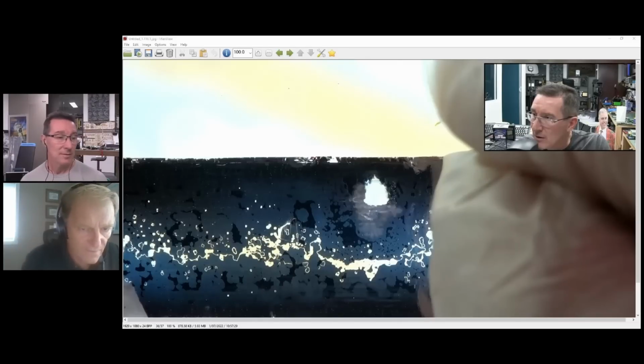So when you get those little micro arcing points, you actually vaporize that electrode material, and as it cools, it precipitates around that failure site. So if we could blow this up a little bit more with a SEM or something like that, we would see a little dark halo around that white point of failure. I might put this under the microscope and see if I can see that.